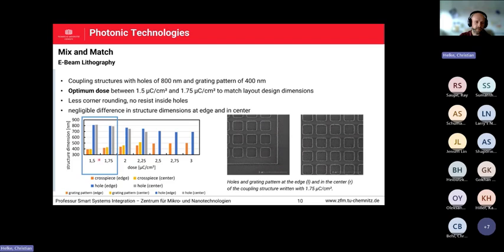And so we concluded from the CD measurement after the e-beam itself that we are in the range of 1.5 to 1.75 microcoulomb per square centimeter to get really nice structures, meaning here at the edge of this array, and also in the middle of this array, showing that the structures look nearly the same. So the PEC works, and the dose is also right, showing really nice structures, which then can be patterned into the silicon nitride layer below.